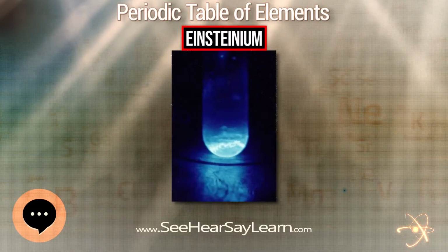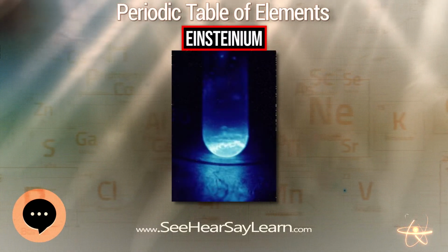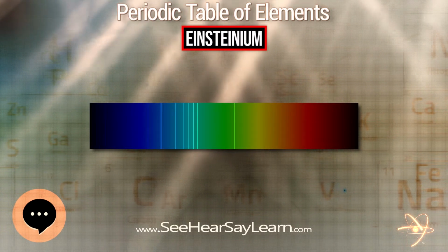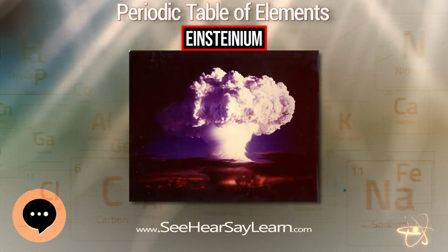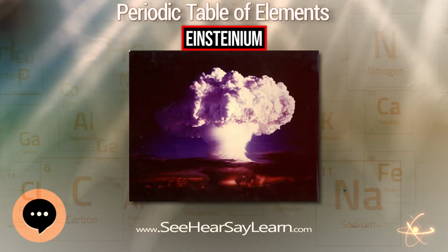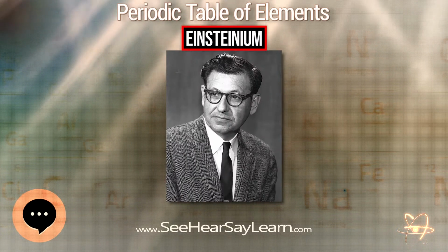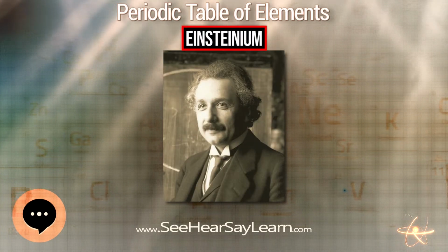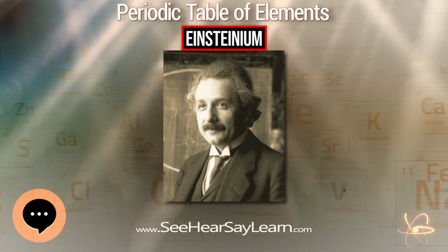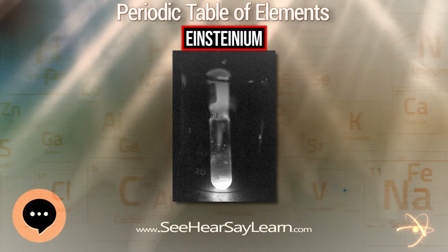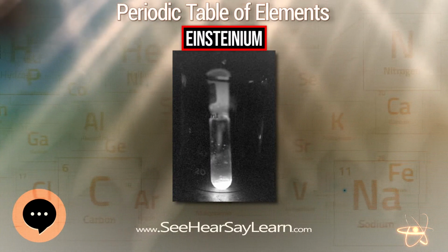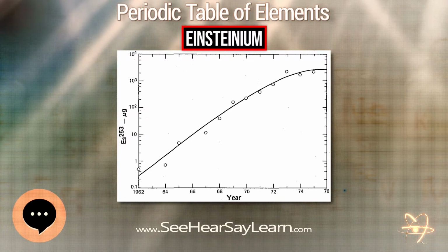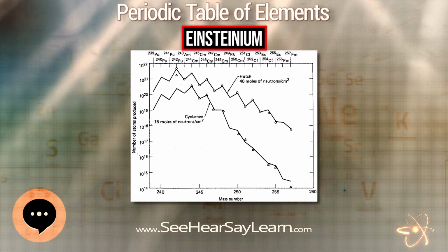The hexagonal phase is isotypic with lanthanum oxide, where the Es3+ ion is surrounded by a 7-coordinated group of O2- ions. Einsteinium halides are known for the oxidation states +2 and +3. The most stable state is +3 for all halides from fluoride to iodide. Einsteinium fluoride can be precipitated from Einsteinium chloride solutions upon reaction with fluoride ions. An alternative preparation procedure is to expose Einsteinium oxide to chlorine trifluoride or F2 gas at a pressure of 1-2 atmospheres and a temperature between 300 and 400 degrees C.